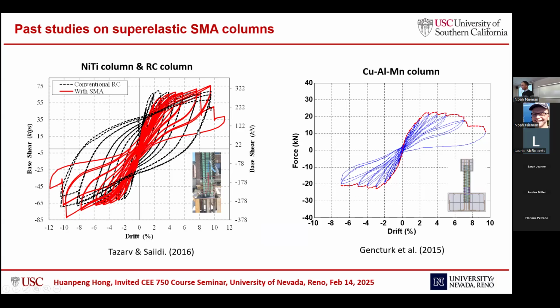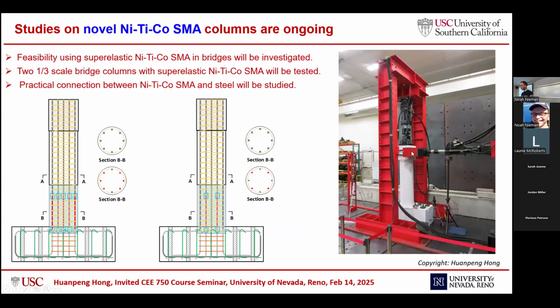Here we see that compared with the RC column, the residual drift of the shape memory alloy column is much smaller. For the copper aluminum manganese column, it has lower yield strength, so maybe the capacity is lower and also the stiffness is lower. But speaking of the recentering capacity, such as the residual drift, it is still really good.